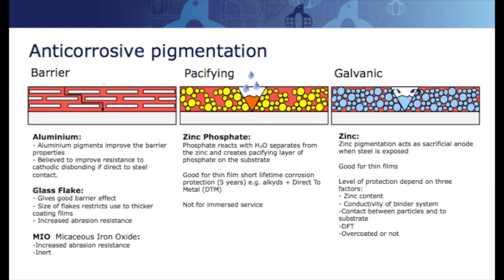Slightly overdone there. The amount of zinc phosphate used in epoxy coatings is just a small amount, so it won't affect it too much. But still, to my mind, zinc phosphates don't belong in an epoxy coating. They do belong, however, in alkyds and short-term life cycle coating systems. So there is a place for zinc phosphates. I'm not against them completely, but in a long-term protection, they don't really belong there.